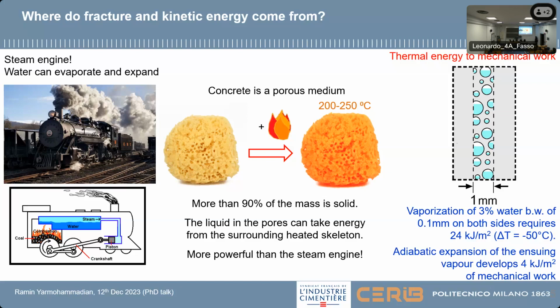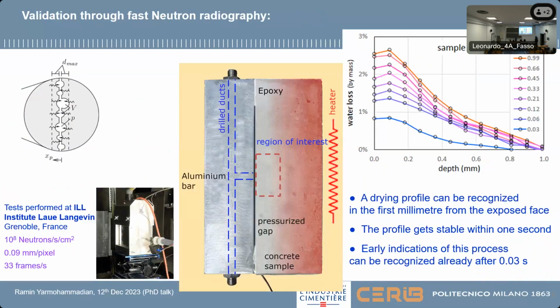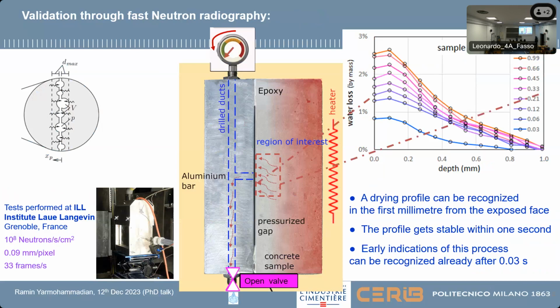To verify all of this, to understand how much concrete is engaged in such an explosive event, we started to test concrete which is heated on one side, with a gap on the other side. We used neutron radiography. Neutrons show hydrogen, and water contains hydrogen, so we can understand how much water there is in each radiography. When we heat from one side, the gap on the left side is pressurized, and then we suddenly open the valve to see how deep the layer engaged in such an event is. You see the results: just 1 millimeter depth is engaged in a very small fraction of a second. In 0.03 seconds, we are dealing with just 1 millimeter depth of concrete, which is vaporizing and giving vapor to the crack.